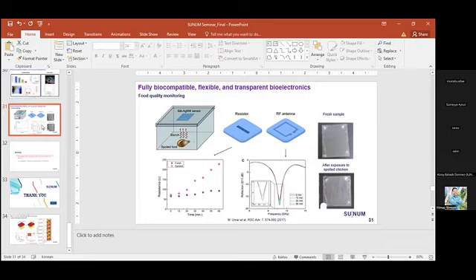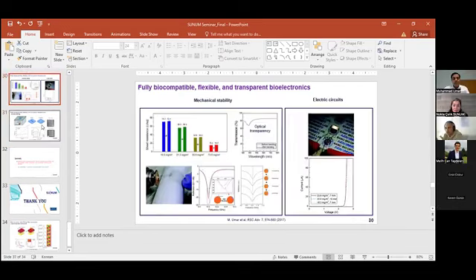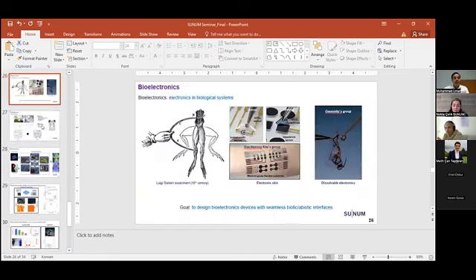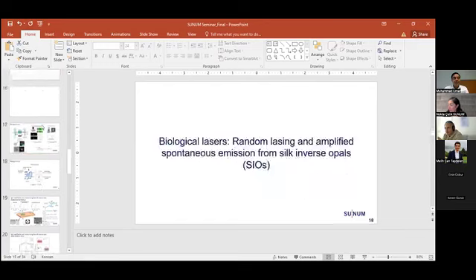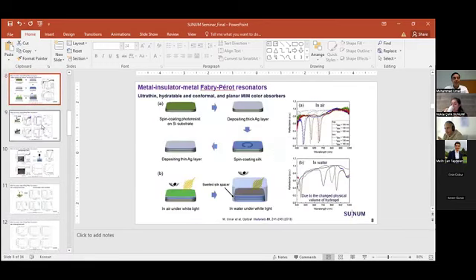Whenever you create the hydrogel in between the films, if you keep the distance between those two films constant by forcing it, because after hydrogel formation it is swelling, so if you diminish that swelling. Sorry, I misunderstood. You mean the first part? This one, right? So this is not the spin coating, this is the deposition. This silver is E-beam deposition. All right, I got the point. And then the silk thickness was controlled by spin coating.